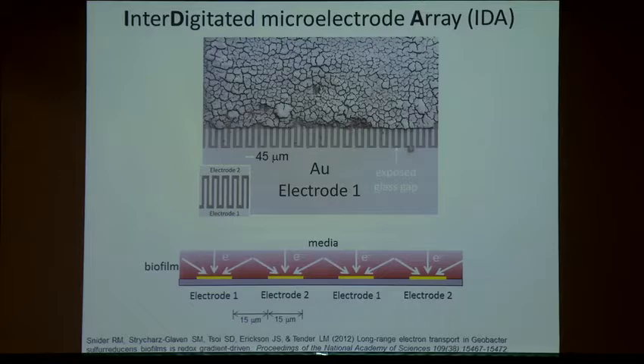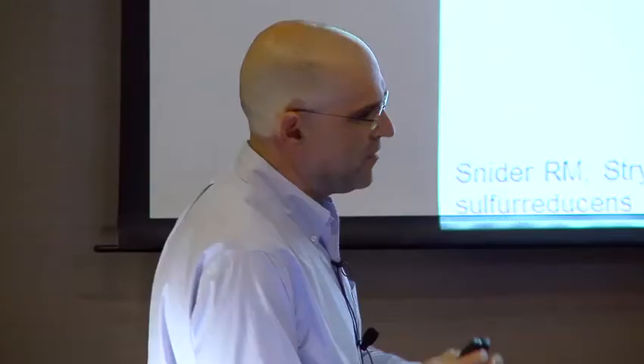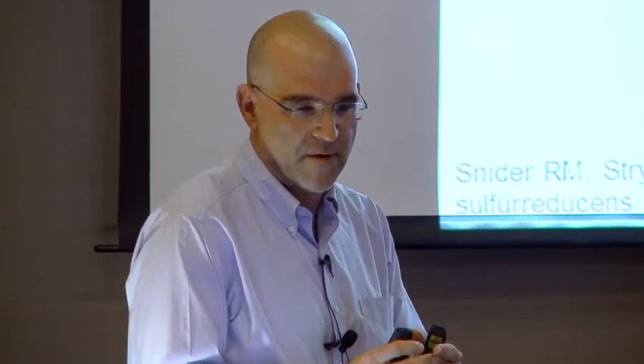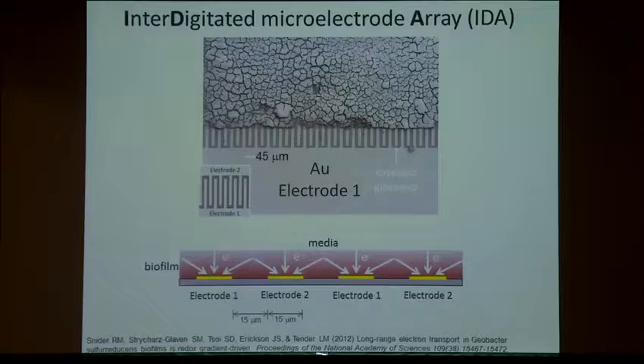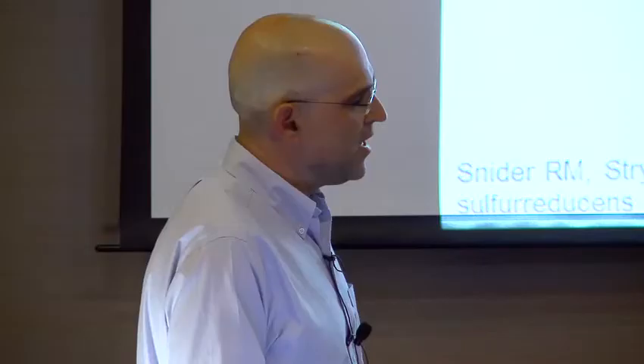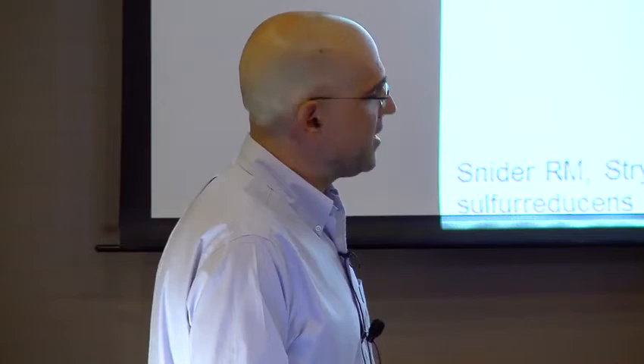And the beauty about this is that it combines essentially a really long gap that's separating these two electrodes into a very compact form. So we have a total electrode area on the scale of a few square millimeters, but the gap that's separating these electrodes, if you took the sums of this gap and this gap and this gap, is 48 centimeters. And so in an experiment where we're actually passing charge from one electrode to the other, that gives us really high signal to noise in our measurement.